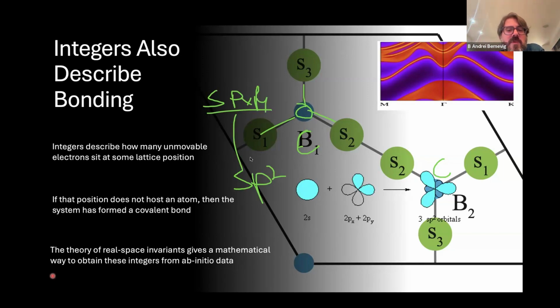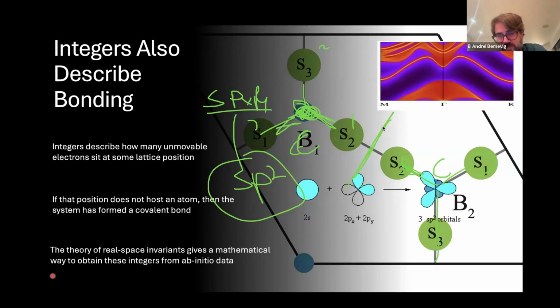These atoms sit in the middle, but because these orbitals, the sp2 orbitals, are strongly hybridized, these three orbitals, which really initially sit on the carbon atom, they can actually split along the bonds. And because they split along the bonds, they can form 1, 2, 3. There's three orbitals on site. They're going to form three orbitals on the bonds. But now notice that there's another three orbitals coming from this guy in graphene, okay? And now notice what happens here. Here, no atom lives. This is called the Kagome site, but there's no atom that lives here.